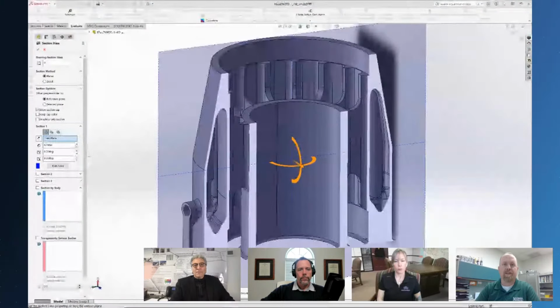So powder coat, obviously you have to have access to the part to be able to spray the powder on. Same with a wet paint process. But something that a lot of people might not know is coatings like anodize and a lot of different electroless coatings or electroplating processes have to have access. They won't coat internal features. So as we've run into parts that have internal features that require some sort of corrosion resistance, it's been really tricky to find suitable coatings.